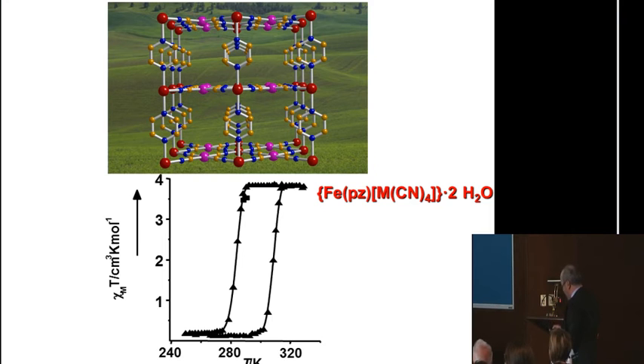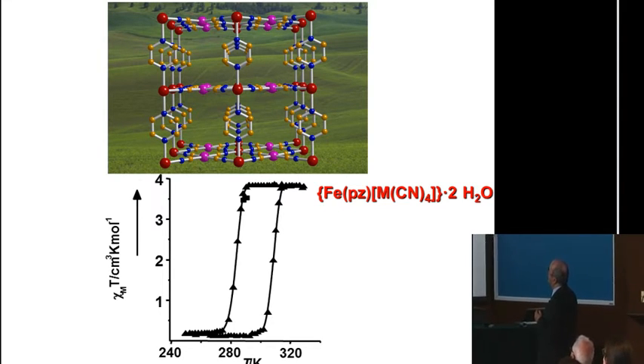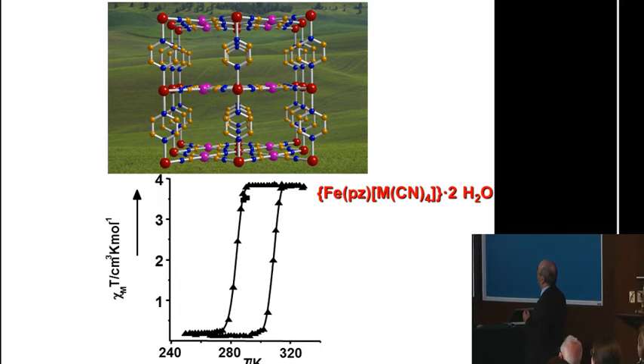So then, in the case of strong interactions, for example, if we take this molecule here, we call it a polymer coordination molecule. You have the iron 2 here, you have pyrazine here, and then you have nitrogen, carbon, nickel, and then iron. So then you have a 2D polymer in the surface, and then two planes here are connected by this pyrazine here. So then everything is connected, and then you have a polymer. We call it a coordination polymer system, okay?